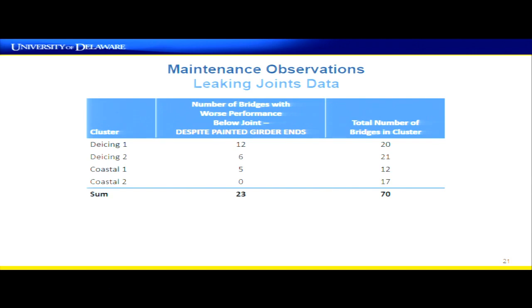For the bridges that we looked at as part of the cluster study, 70 bridges, 23 of them had corrosion that was worse at the joint, and it's not just limited to the joint. Once there is a problem at the joint, the water from there travels longitudinally along the rest of the bridge. So 23 out of 70 bridges had a problem at the joint, despite having the end of the girder painted, according to that 1989 technical advisory. So that's something we should do. We should paint the end, but we shouldn't think we've painted the end and therefore everything's fine. It's very critical that we maintain these joints. It's a very cheap solution to preventing corrosion.